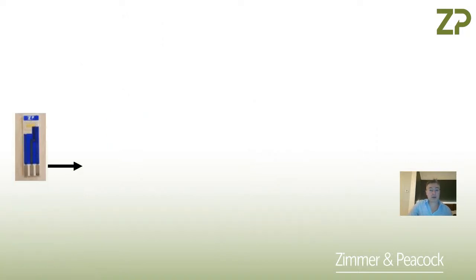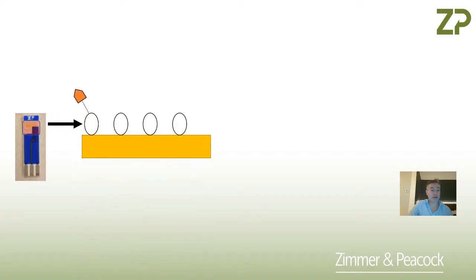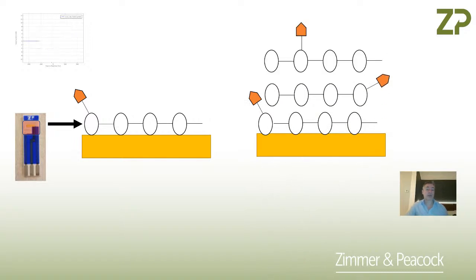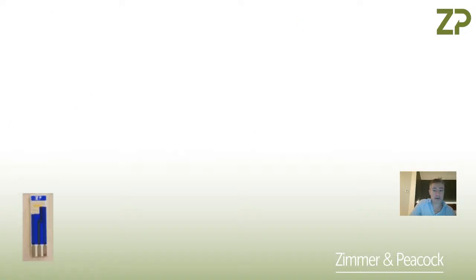Now, to contrast with that, you could also take monomers which had, in this idea, a key functionality. So it was opposite to earlier on. You could do cyclic voltammetry and you can have a functional electropolymerized surface. This is almost like the opposite of what we were showing earlier on. We have some functional groups on it, but this is what I'm calling the key moiety. Earlier I called it the lock moiety. But now this is not a MIP because we didn't do it in the presence of a template. So let's contrast that now and do it.